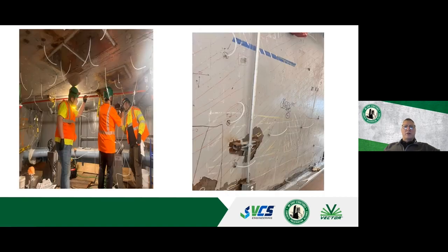I wanted to show this one. Actually, I don't think I have the slide blown up close enough, but you can see, why all these tubes? What's actually happening in these situations is that there are voids in the concrete behind. It's not cracking. You're not seeing cracking. So they drilled in and we are repairing the voids with the epoxy injection. This is almost like a packer was installed, and then you added this tubing so that we can do the injection.